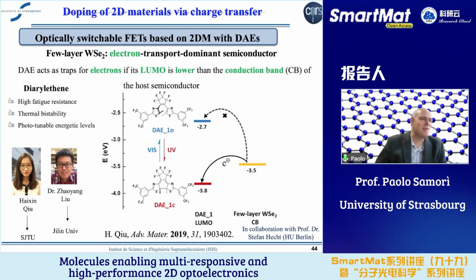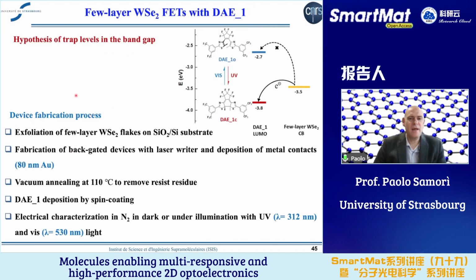And what I want to stress is that when a dopant has a state inside the band gap of the semiconductor, it will behave like a trap for the charges of the semiconductor. Whereas when the level is out of the band gap, the interaction with the semiconductor is purely electrostatic. And so this is what we have been doing. Diarylethene, by the way, has high fatigue resistance, high thermal bistability, and a highly phototunable energy level. So this is the way we performed the experiment.